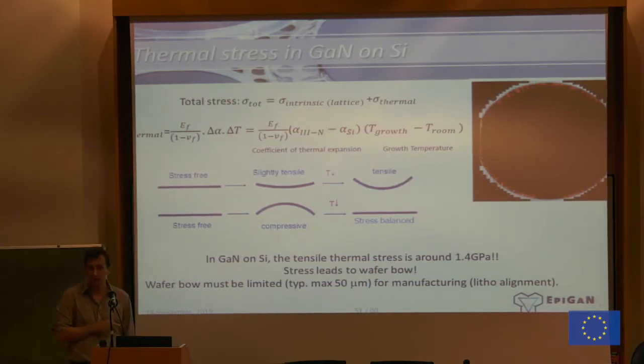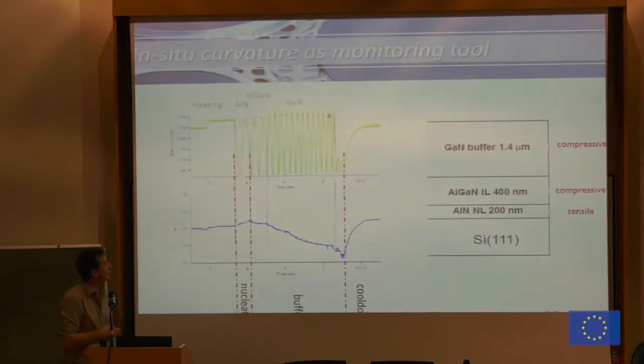Still, a flat wafer is not a stress-free wafer, it is a stress-balanced wafer, which makes these wafers quite a bit more fragile than the reference. You can actually monitor this while you are growing, which is depicted here. So we will grow this structure. We start from silicon. We do an aluminum nitride nucleation layer. We grow an AlGaN layer and then a gallium nitride.